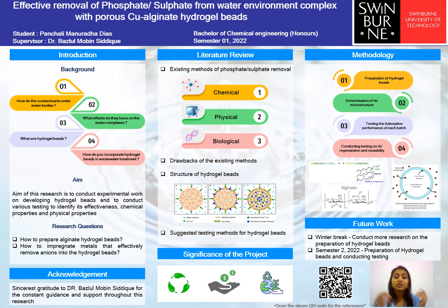This is to ensure the cross linkage. So after the beads are aged for about 12 hours in this solution, they can be passed through a hydrochloric acid solution of 0.2 mole per liter concentration, and 6 hours they will stay there, and once they are done, using deionized water you can adjust the pH until it reaches 7.